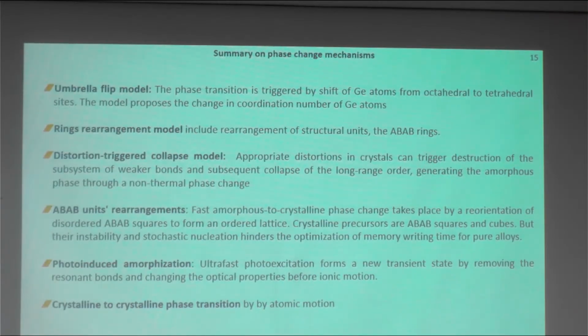In the photo-induced amorphization, ultrafast photoexcitation shows the formation of an additional phase: first the cubic phase loses its metavalent bonding and transforms to the covalent state, and then it melts by energy transfer to the lattice system. The phase is heated up and transforms to the liquid, and then on cooling to the amorphous state. We also considered the crystalline to crystalline phase transition between cubic and vacancy ordered, and vacancy ordered to trigonal phase. Here we saw that it occurs by atomic motion over very short distances.